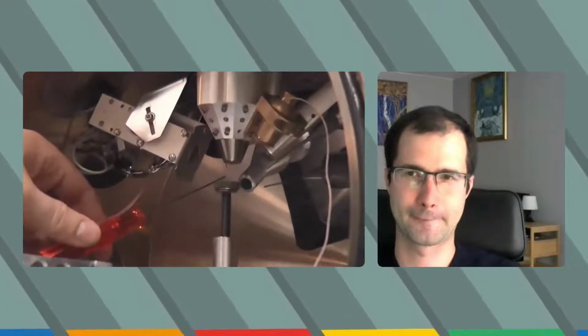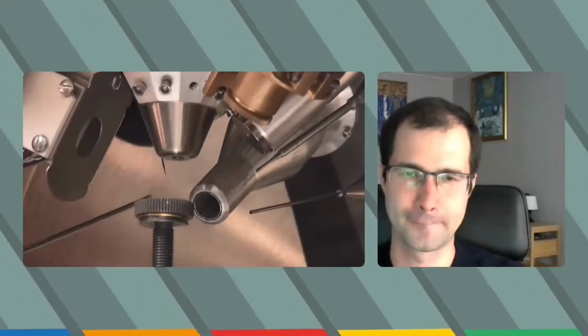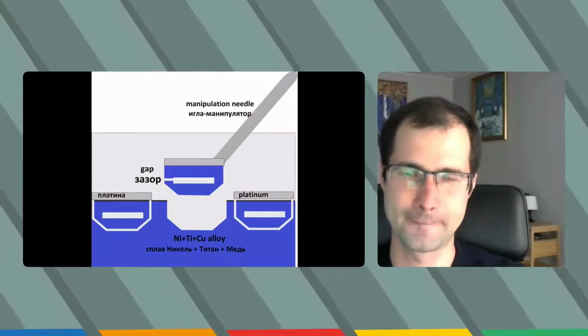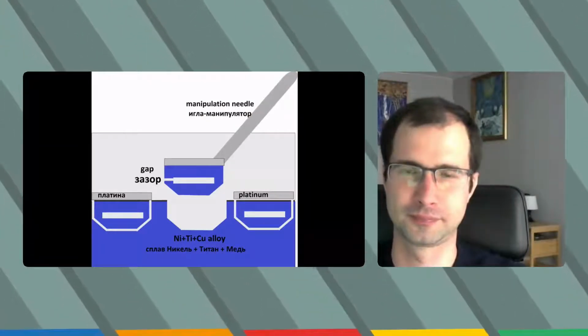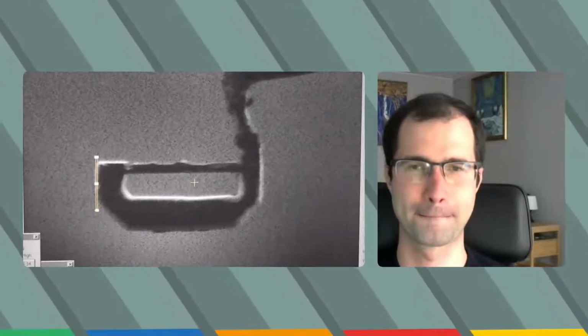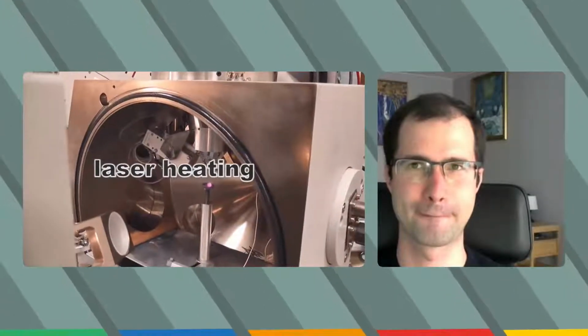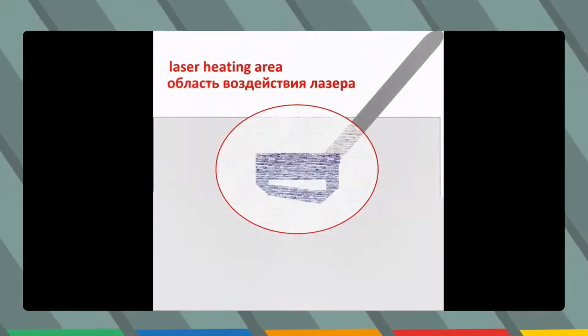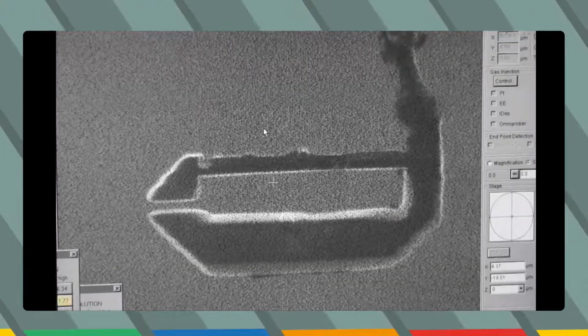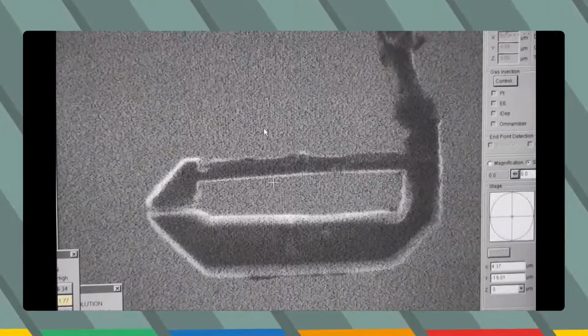Inside the microscope, there is a manipulation needle. This needle connects with one of the plates and moves it. The initial plates are marked in blue color. Let's look at how it goes. The needle is a thin tungsten wire that carefully connects with the plates, then platinum sticks them together. After that, the nano tweezers tip is sharpened, and then we create a gap of 1 micrometer. Nano tweezers work because of laser heating. The laser is also placed inside the microscope. Platinum heats up to 60 Celsius and compression occurs. When the laser is switched off, the plates are unclenched.